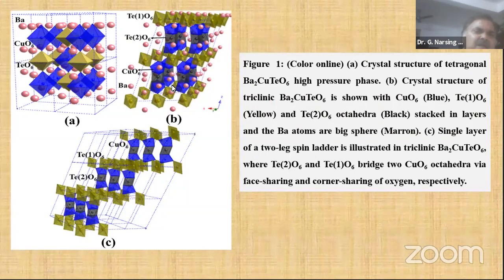This is a tetragonal structure, A. This, B, is a triclinic structure. What I am interested in is this triclinic structure. So there is a combination of copper oxide, this CuO6. Then there is tellurium as well, and the tellurium has 2 positions: one is Te1 and the other is Te2.